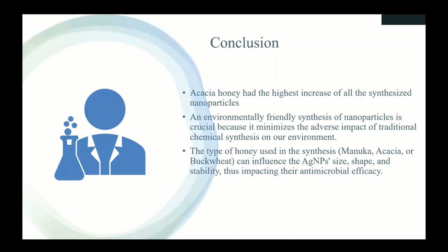So these are our conclusions. We see that acacia honey had the highest increase for the nanoparticles as a way to inhibit bacterial growth. Because we did green chemistry, this is an environmentally friendly way to synthesize nanoparticles. We use water as our solvent. That meant that we used no harsh chemicals, and we used honey. And because we use honey, that means that we are using natural resources. Now, we do need to characterize our nanoparticles using some type of microscopy or spectroscopy. Currently, we do not have the resources to do that.